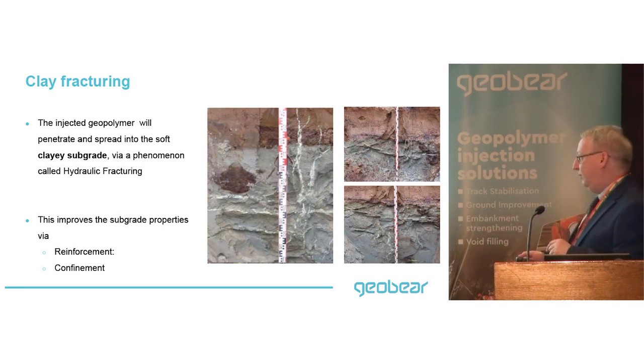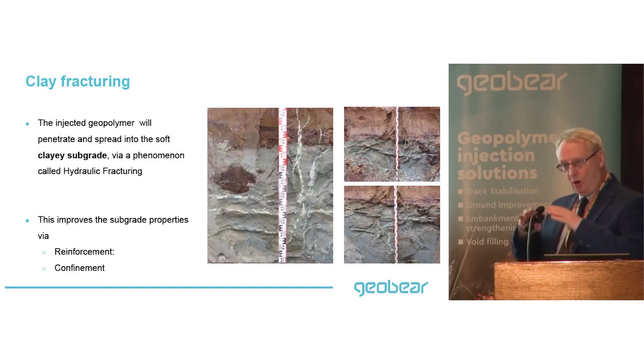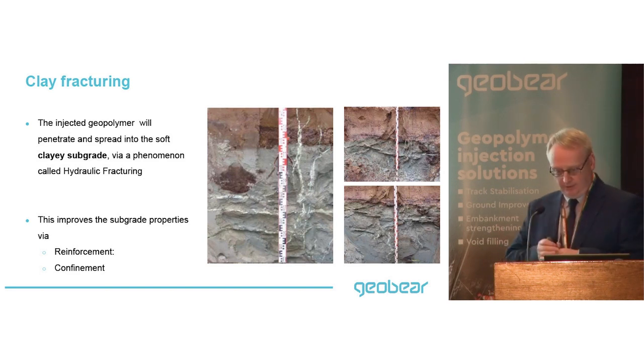That's essentially how it works. We fracture the clay, we fill the fractures with the polymer, and since the polymer is very strong, you get a composite effect of strengthening the clay.